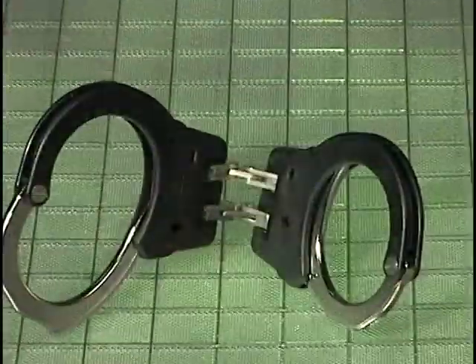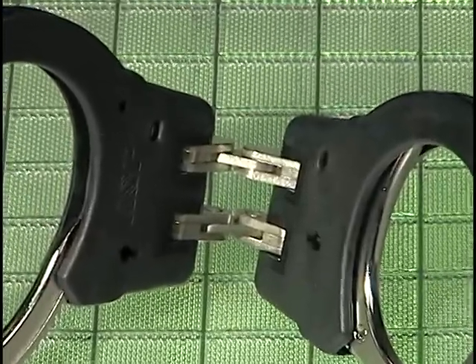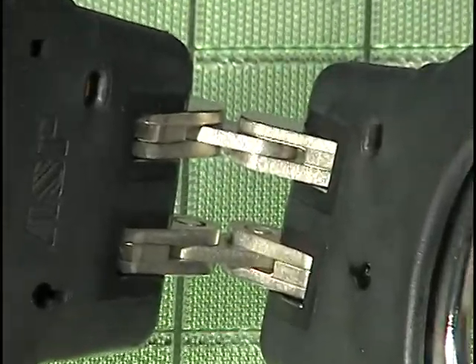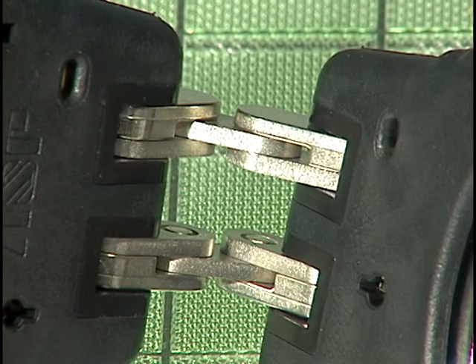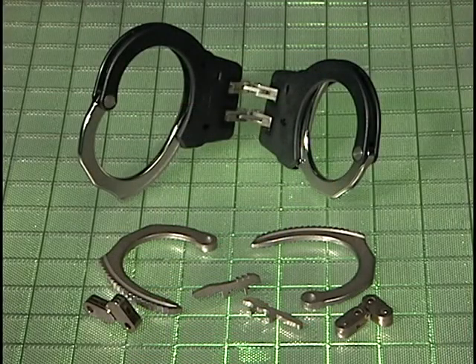12 parts are made from 3 stainless steel materials, and 2 parts are made from MPIF FD0405-60 steel. The 4 main links are made by metal injection molding to a minimum density of 7.5 grams per cubic centimeter and have a tensile strength of 78,000 psi. The other parts are processed by conventional or high-temperature sintering.